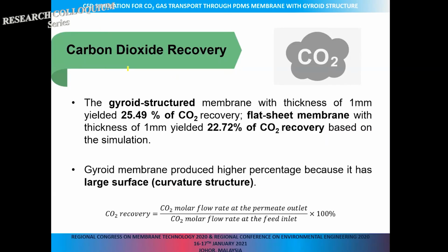For the CO2 recovery, we calculate based on the molar flow rate at the permeate side over the feed inlet. So based on the calculation, gyro structure has a slightly higher CO2 recovery, up to 25% as compared to the flat sheet membrane. These values are actually relatively low as compared to the membrane that has been used in the industry. Usually the CO2 recovery should be up to 80% in order to be used in the industry.